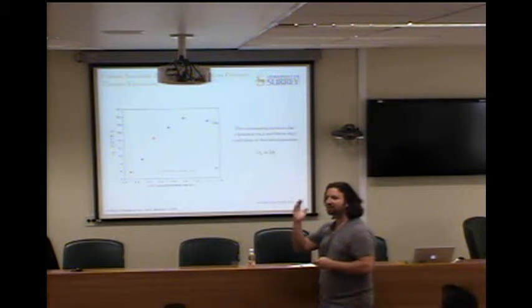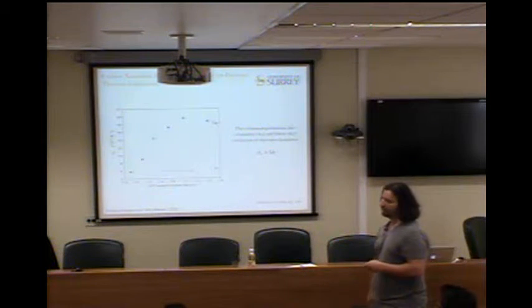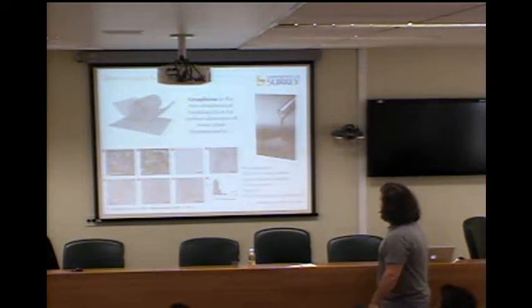So if we look at the volume expansion, so we measure the change in thickness as a function of the temperature, and we do that for different CNT weight fractions, we can see that the overall change in the Z direction is 3 times what one would expect for the volume. Right? So it works really beautifully, and it behaves as a very quick thermal expansion system or thermal sensor.